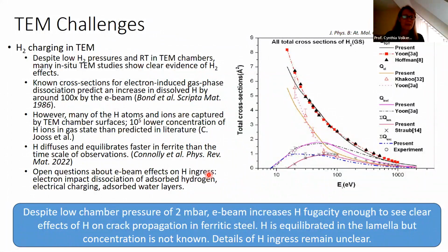Now, there are known cross sections for electron-induced gas phase dissociation. And if one just simply uses those values, we would predict an increase in the amount of dissolved hydrogen over what one would expect for 2 millibars at room temperature by a factor of 100. Might be enough to make some difference.